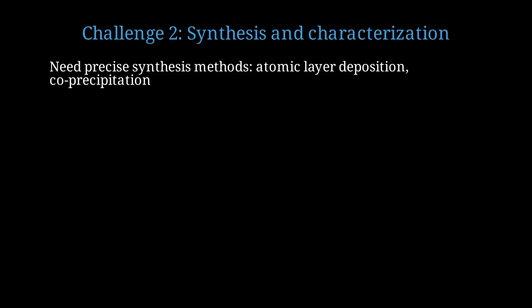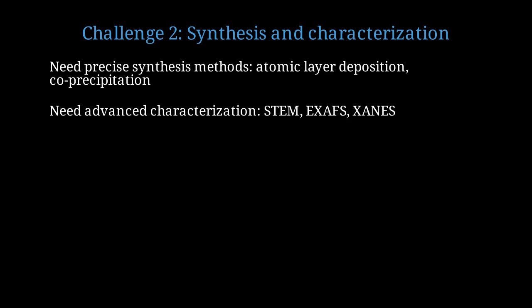The second challenge is making and characterizing these materials. It's not easy to create truly isolated atoms and prove that they stay isolated. Synthesis requires precise methods like atomic layer deposition or carefully controlled coprecipitation and calcination. The metal loading must be very low, typically less than 1 weight%. Characterization requires advanced techniques. Aberration-corrected scanning transmission electron microscopy can image individual atoms. Extended X-ray absorption fine structure and X-ray absorption near-edge structure probe the local coordination environment.